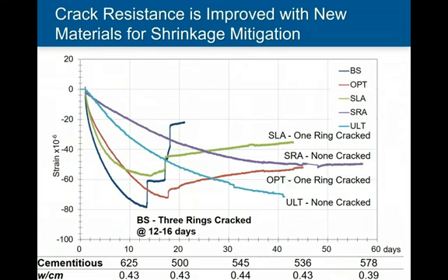Both of those were situations where only one of the three rings cracked. So we're kind of right on the cusp in that case of the cracks starting to become an issue, but it was out past the 10, 14-day mark. So we were really pretty pleased with that compared to what we saw in the control mix, which was all three rings cracking in right around the 2-week mark. So again, a very significant improvement.